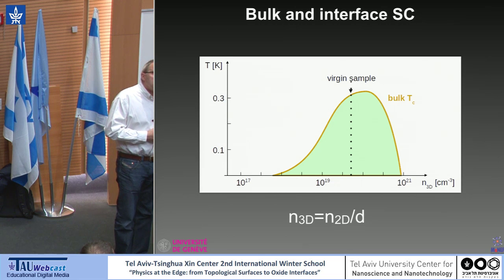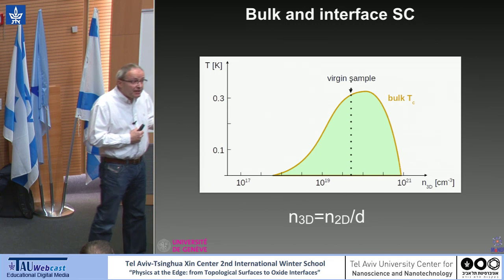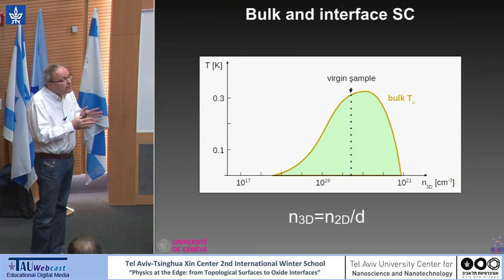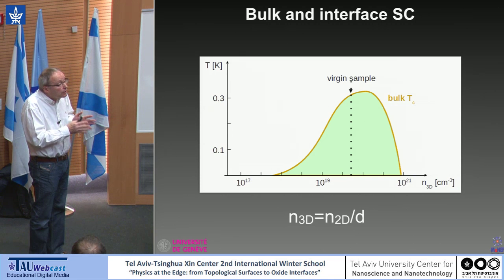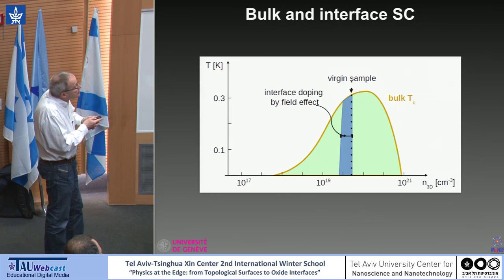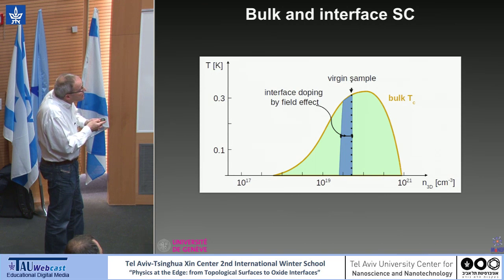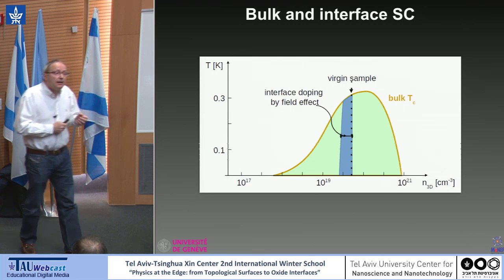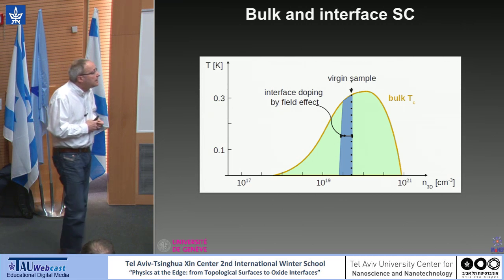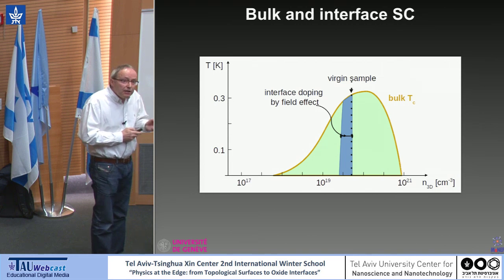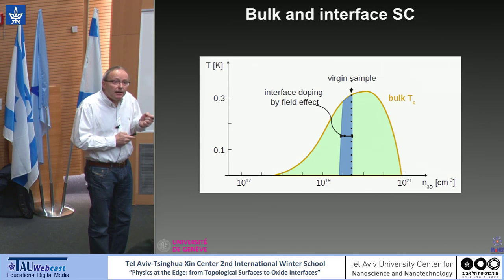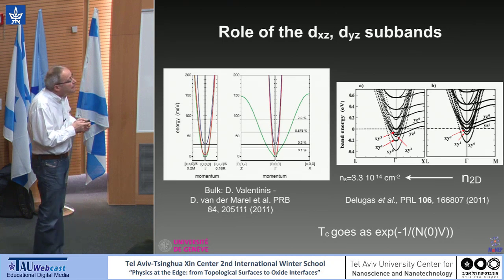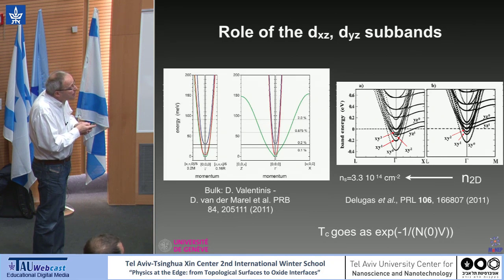But the first thing we noticed is that when you remove carriers from our system with field effect, we know that we can change the carrier density maybe by a factor of 2 or 3, not more. Here, it's a log scale. So it means that the superconducting regime is somewhere here. We're losing superconductivity more rapidly at the interface. And I believe this is due to the electronic structure of the interface. As I mentioned, at the interface we have this particular electronic structure.